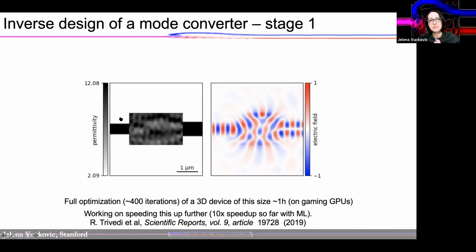So for example, here we're designing a mode converter, a first to second order mode converter between input and output waveguide. What we wanted to do is design it in a footprint that is only about 2 by 1 micron. And this is many orders of magnitude smaller than the traditional way of performing mode conversion, which is adiabatic mode conversion, where to achieve greater than 90% efficiency, you need to do it over hundreds of micrometers on a chip in a waveguide. Here, we wanted to do it with greater than 90% efficiency in a 2 by 1 micron footprint.